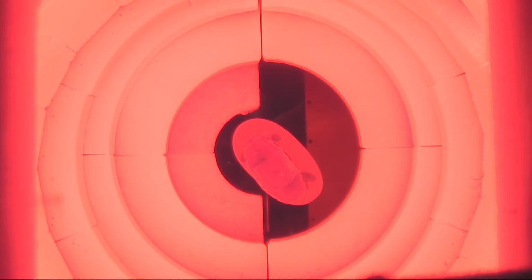So those punty connections, to really make sure they break free when we need them to, it not only comes down to having the temperatures right going into that joint and transfer, but often you'll see us crimp the punty with a cold tool, the metal shears. When you do that, the metal shocks that punty, so it helps it to weaken and break free. But also, just as important is that when you hold the shears there and you tap on that rod, the vibration goes more into the tool that you're holding and not the piece itself. So it's a good little trick to employ, especially when you have really delicate parts like that.